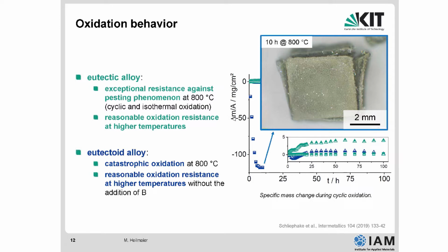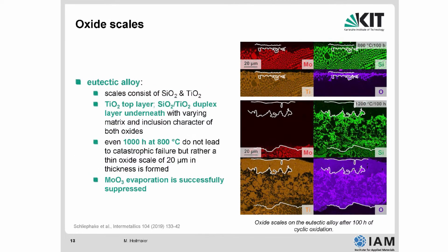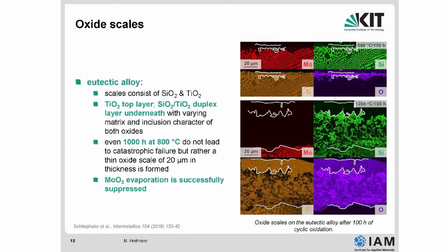But this alloy shows very good oxidation resistance. And of course, without going too much into detail, you can analyze the oxide scales here by doing advanced microstructural characterization. You don't see the oxide scale here on the top because you cannot see a silica scale. This is not easily viewable with SEM. But what you can see is that the oxide scale in the eutectic alloy consists of silica and titania. And both oxides form a mixed scale, and this mixed scale shows surprisingly high oxidation resistance for this particular alloy.